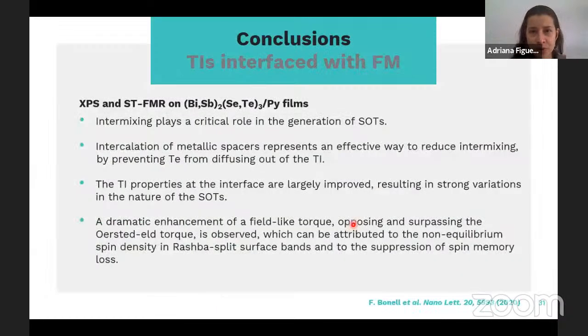So with this, I finished my first part about the TIs. I just wanted to show you that we investigated TI interfaces with a series of metallic ferromagnets, using spectroscopy and FMR measurements to study the spin-orbit torque. And in that case, the main conclusion, or the take-home message, is that intermixing plays a critical role in the generation of spin-orbit torques at these interfaces, and that it is important to make sure we control such interfaces, not only in a chemical way, but also because it affects the spin-orbit torques that happen at the interface, and that is reflected in their spin-orbit properties.